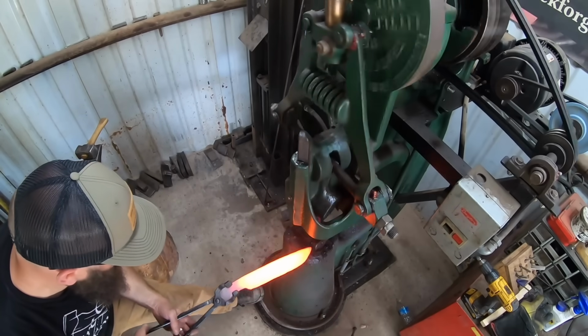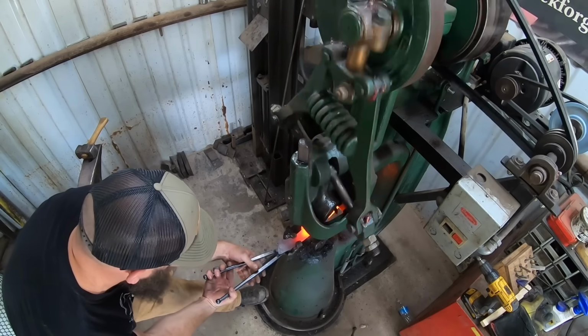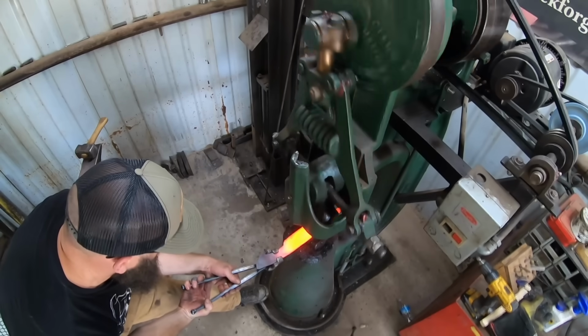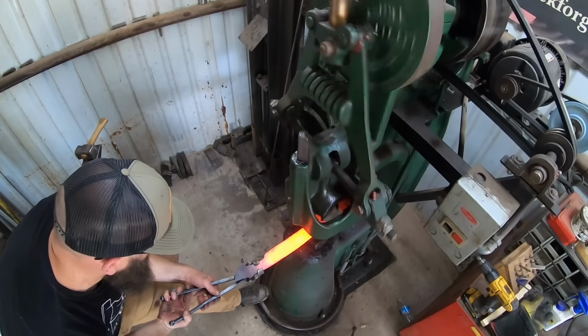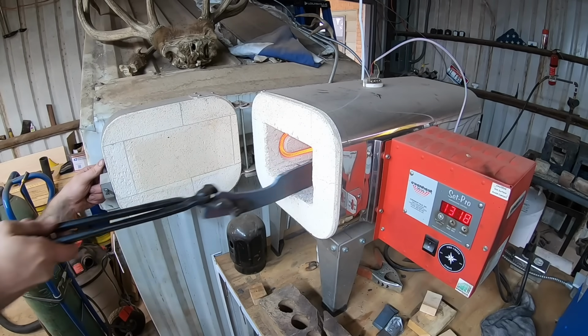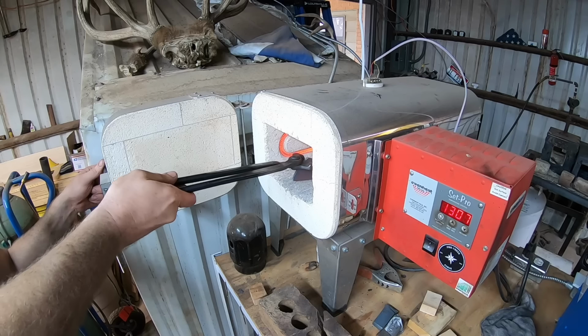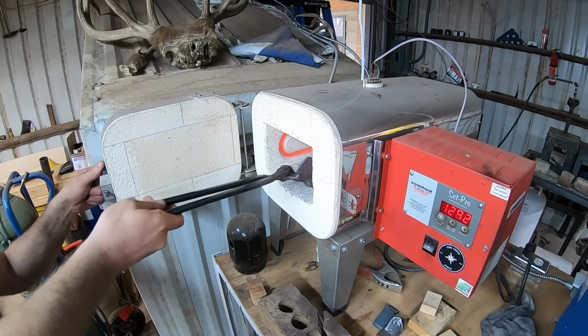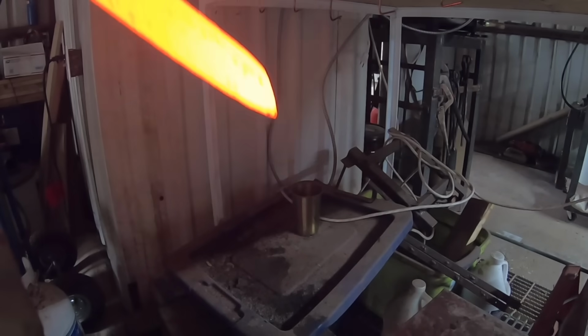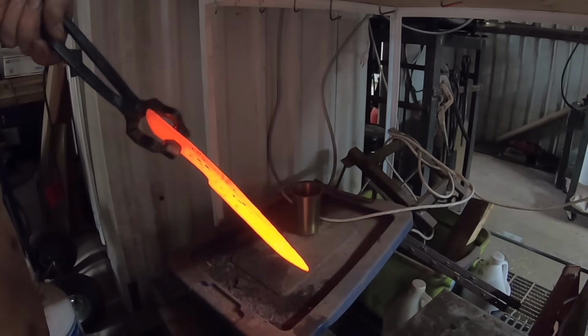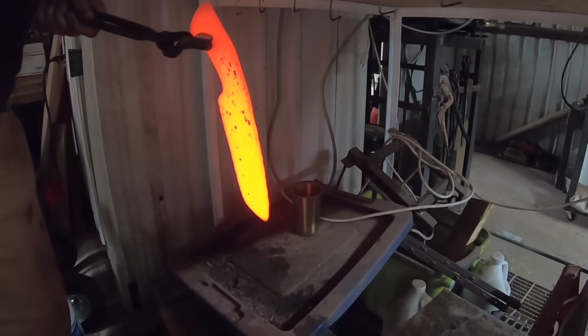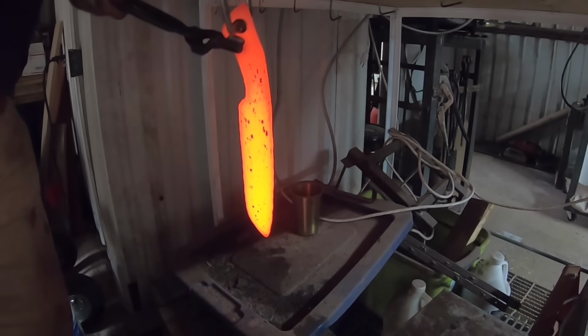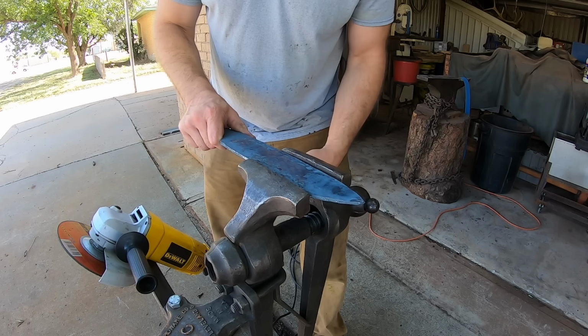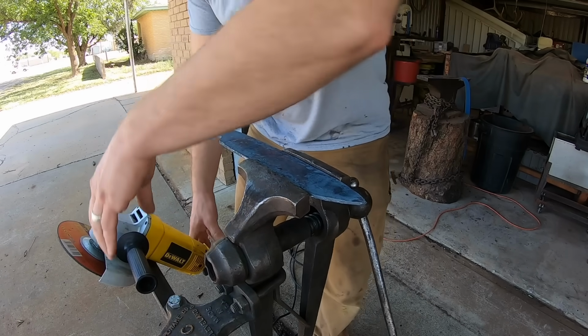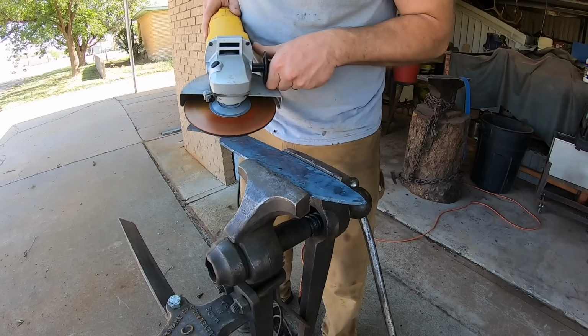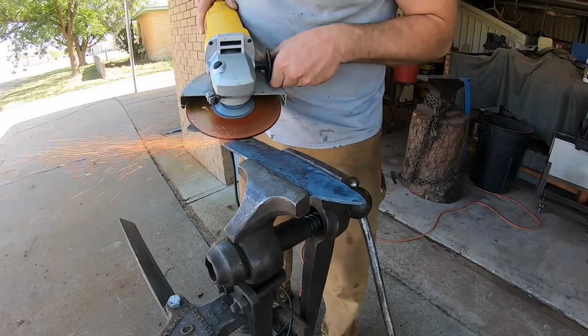Got the blade forged out nicely. I'm putting in a little bit of a distal taper here, flattening things out using the 50-pound Little Giant, and it's going pretty well. So the forging process creates a lot of internal stress in the steel and a lot of discontinuity, if you will. We need to get everything back to a more homogeneous state. The grain size needs to be the same across the steel. This is all important for setting ourselves up for a good, strong blade in the heat processes to follow.